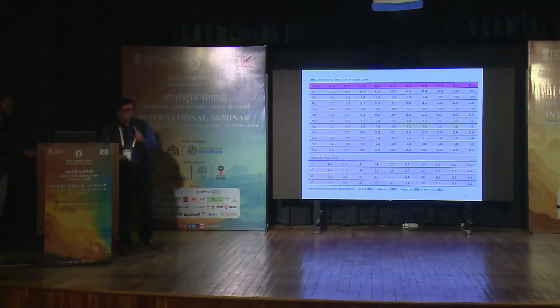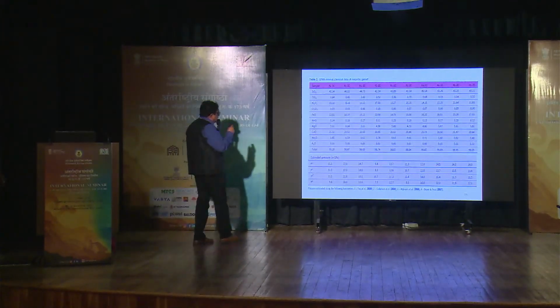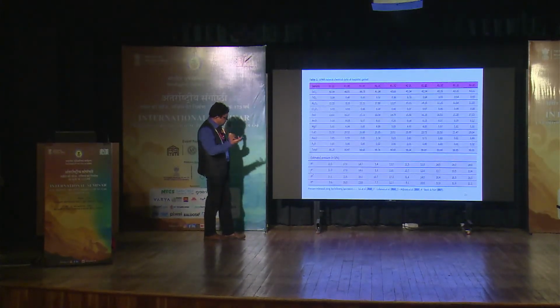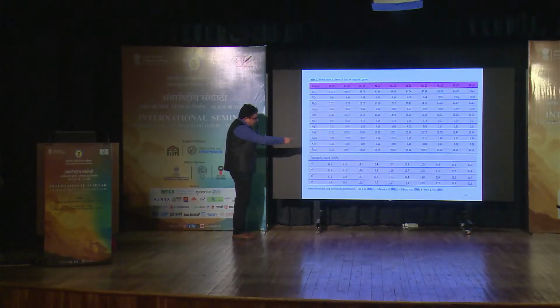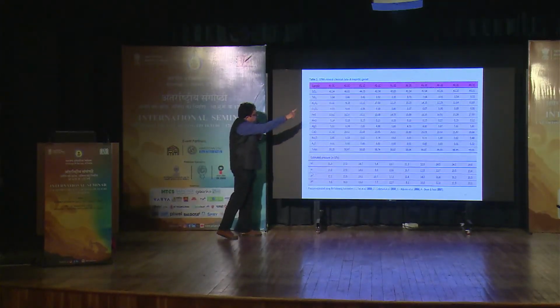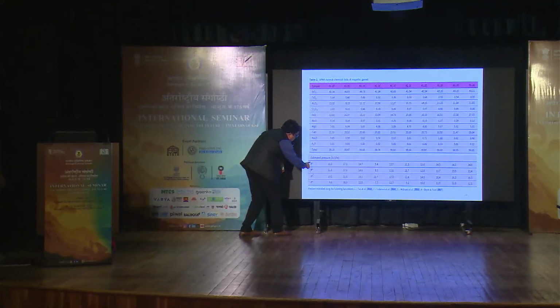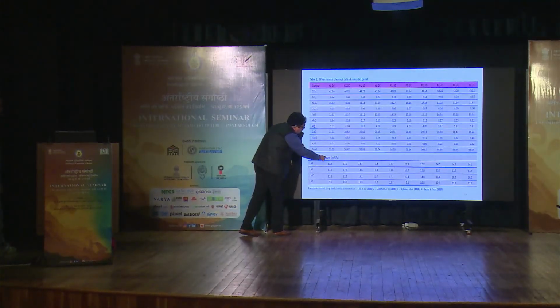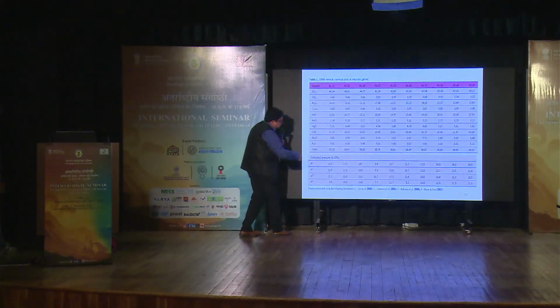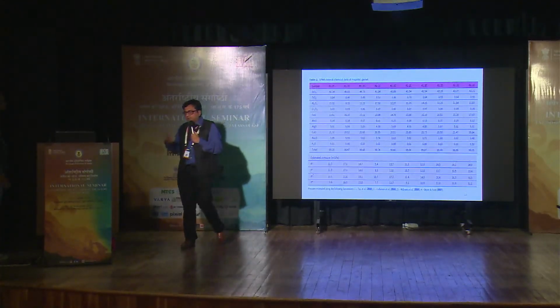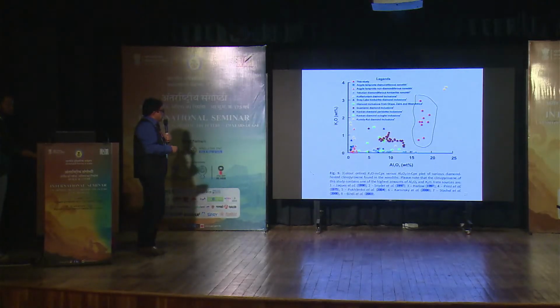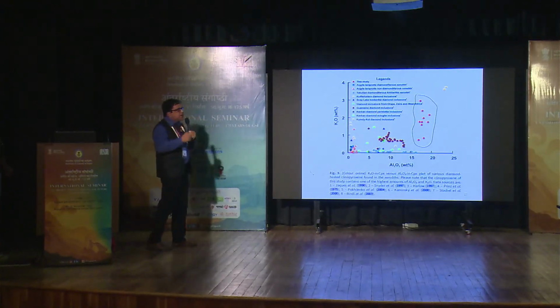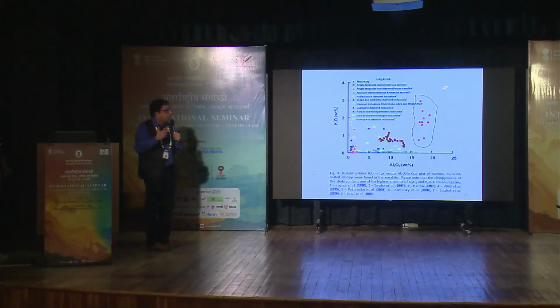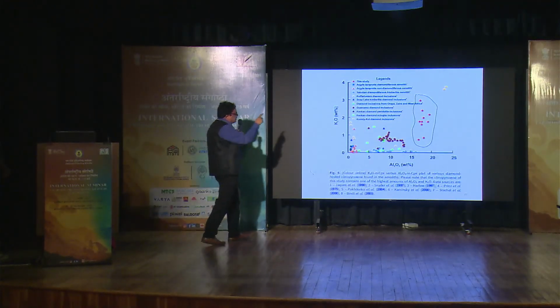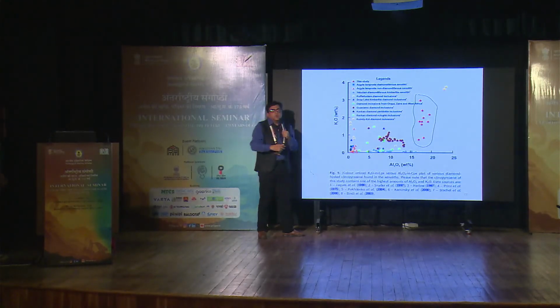Next. Then we calculated the pressure from which this majorite garnet was derived, because there are very good geobarometers available in the literature. This is the data generated by us, and these are the pressures computed based on geobarometry. You can see they were all derived from a range of pressures, 11.3 to 17 gigapascals. So they are coming from extremely deeper depths than we can think of. And we have also analyzed the CPX present in our sample, and that turned out to be a potassium-rich omphacite, and potassium-rich omphacites are recorded from diamonds as inclusions.